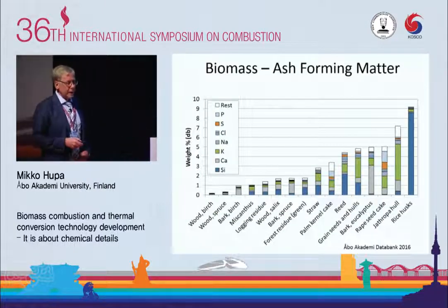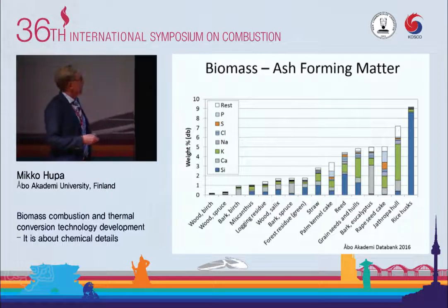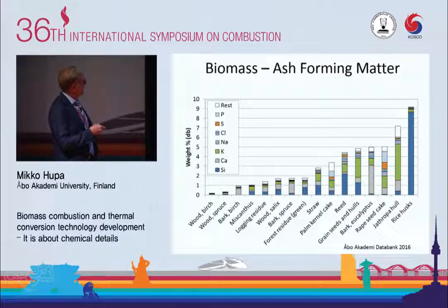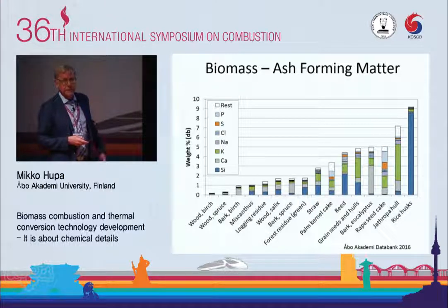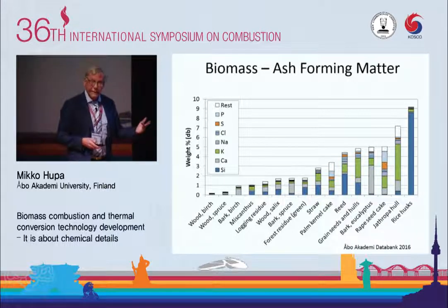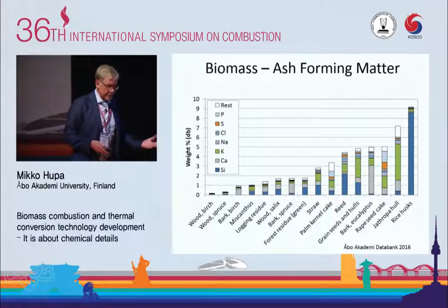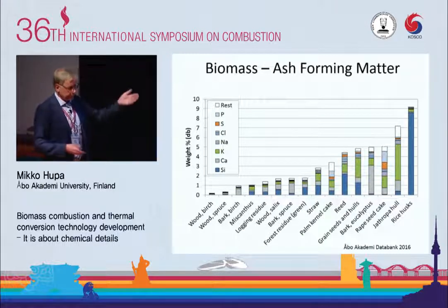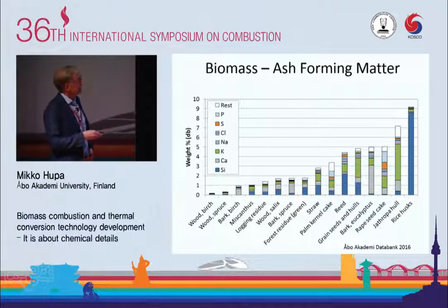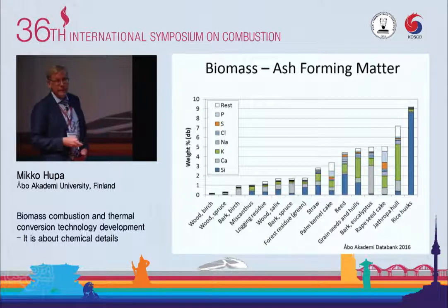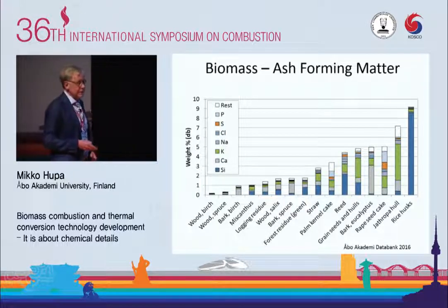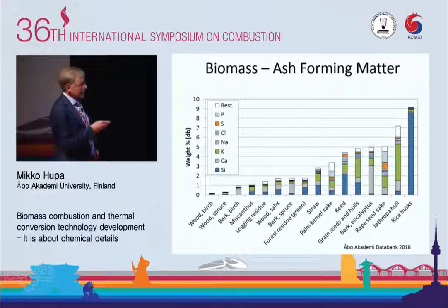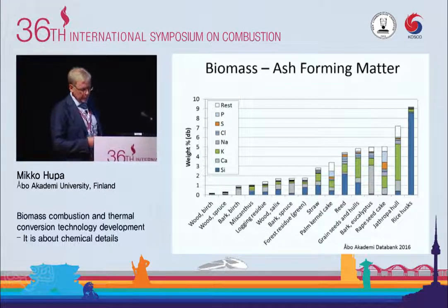Here is a summary of ash-forming matter in different biomass fuels, and you see here that wood has a very low ash content, and the champion here is rice husk, where the ash-forming matter is 9%. This is percentage elements, so if we take it as an oxide, then it's silicon oxide. This is almost pure silicon oxide. It's 20%. So rice husk is a very interesting biomass fuel also. I will come back to the composition of this just in a moment.